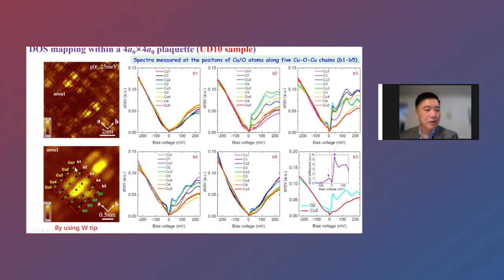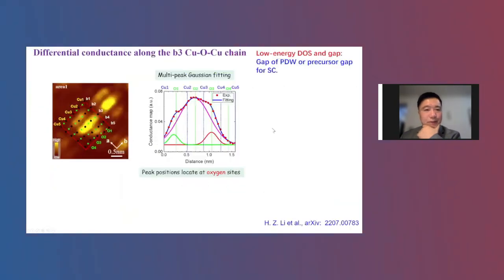So it seems that this very unique 4a by 4a block is very important. And it shows this kind of internal nematic state of low energy density of states, that shows some kind of small gap, which looks like the superconducting gap, okay?